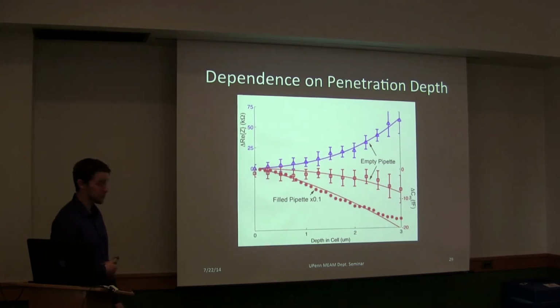So we can correlate the signal change that we're getting with the depth that we're actually penetrating the cell at a submicron scale. We can also compare that to data from a filled pipette, such as the microinjection pipettes that we had earlier, and show that this is actually the signal multiplied by 0.1, so it's 1/10 the scale. And you can tell that the signal is much, much greater when you have fluid inside the pipette, basically confirming our previous analysis. So that's one microelectrode application of CNPs.